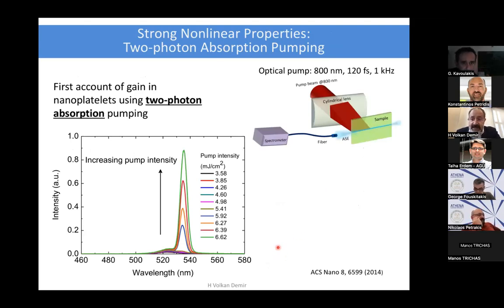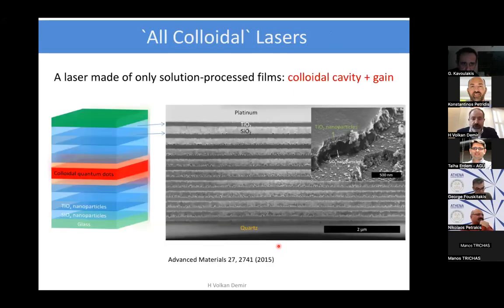In this case, we are using actually nonlinear regime. And to understand how this was possible, we also measured their nonlinear absorption cross-section. And we found per particle, it is over 1 million Goeppert-Mayer, which is extremely high. As a matter of fact, one of the highest we could find in the literature. This is good, and we need to obviously understand how this behavior compares to the existing colloidal quantum dot work.